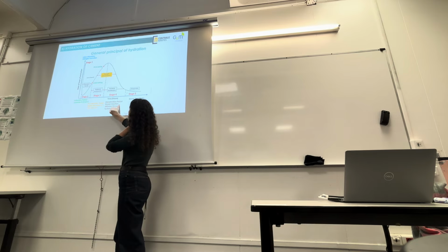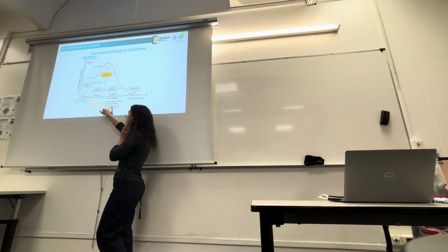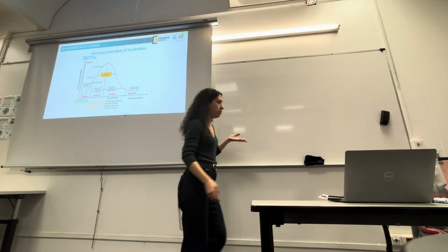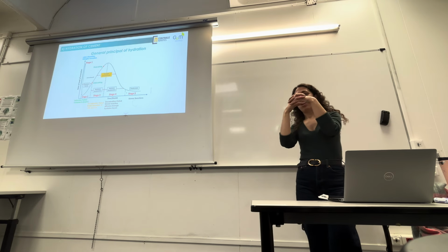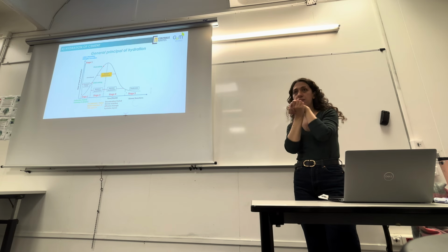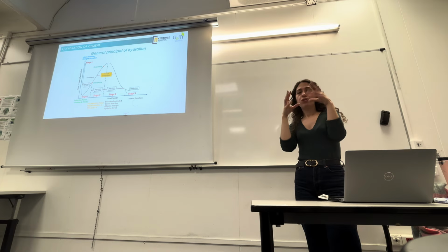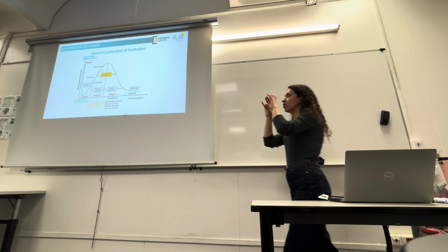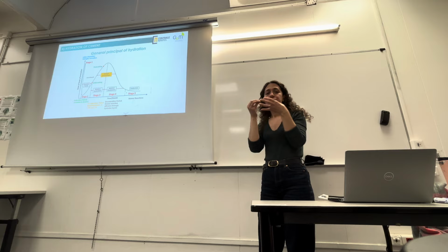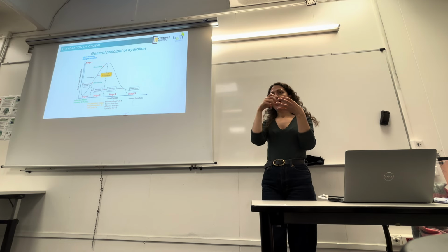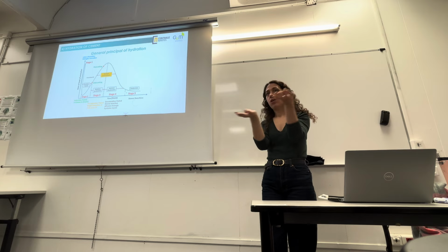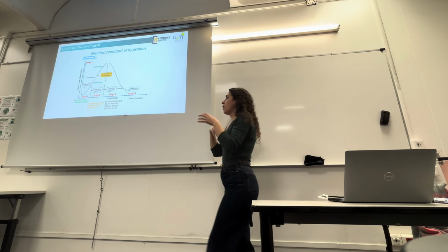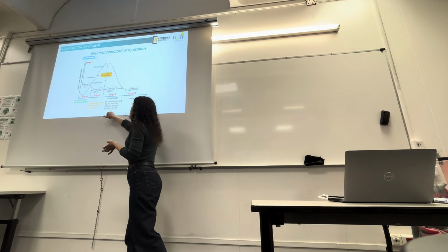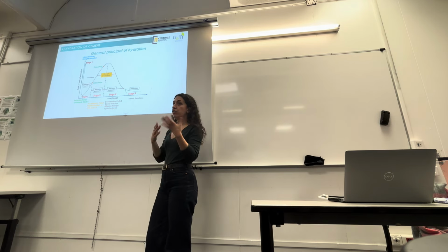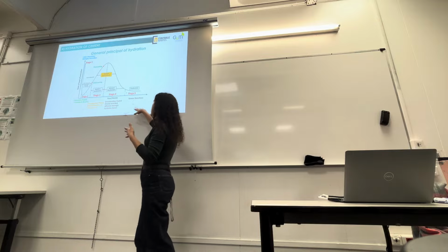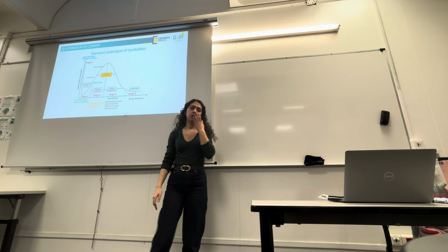Then you have stage 4, the deceleration period. So slower reaction, diffusion through the hydrate layer. Yes, because now your grain of anhydrous cement, that is your producers of ions, they are covered with hydrates. So it's harder for water to reach these anhydrous and to dissolve these anhydrous ions because they are completely covered with hydrates. But the diffusion through hydrate layers still occurs, and you still have the hydrations that continue for time. And then you have steady state with slower reaction.